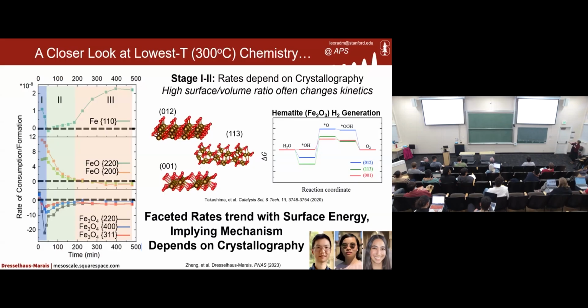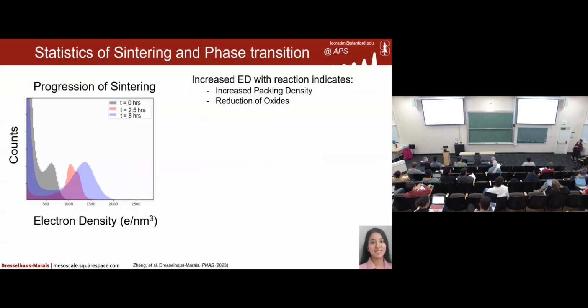However, what you'll notice is that actually on step 3, suddenly that mechanism no longer really depends as strongly on the orientation of the crystal. So that tells us now that the crystallography has less to do with that last step. Something is happening potentially at a larger length scale.